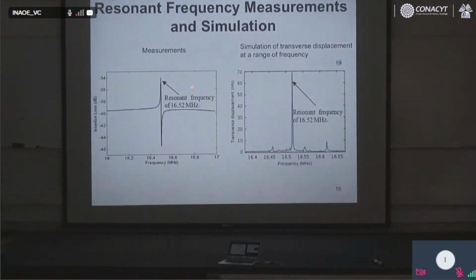And what is here is the resonant frequency. A quartz crystal microbalance does not have a high resonant frequency, the maximum resonant frequency is around 16.52 megahertz, and then using COMSOL, he simulated. This is a very simple simulation. So he managed to get it, and it's based on the thickness of the quartz crystal, the substrate.